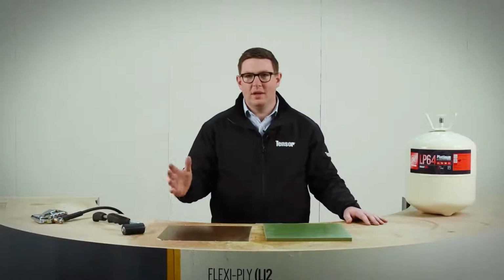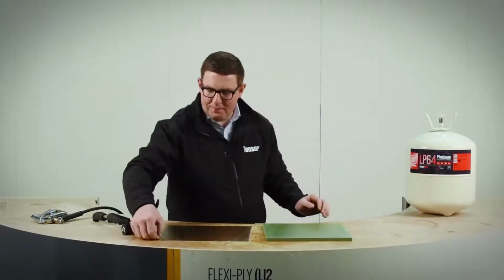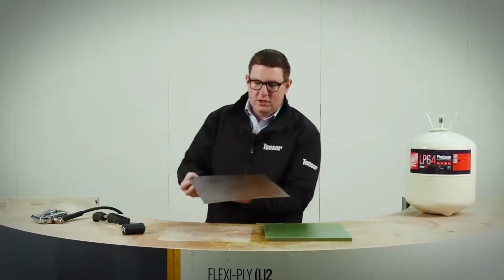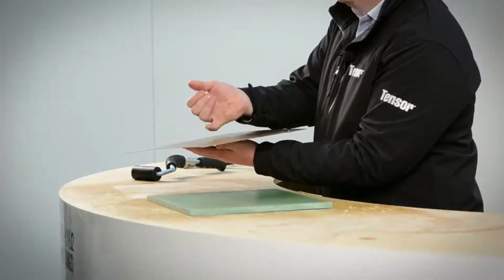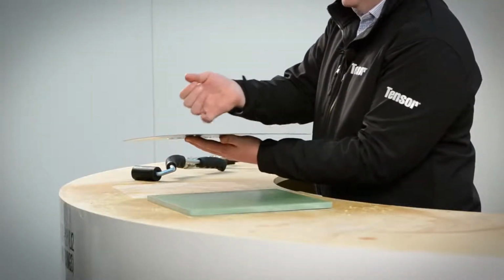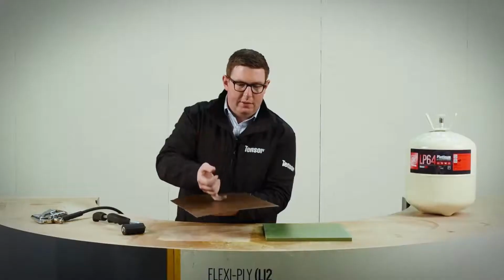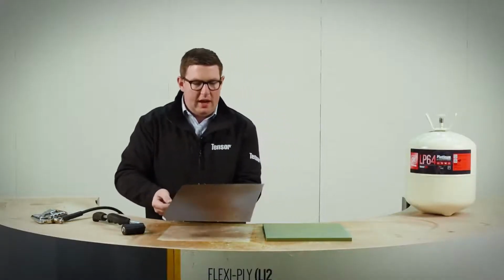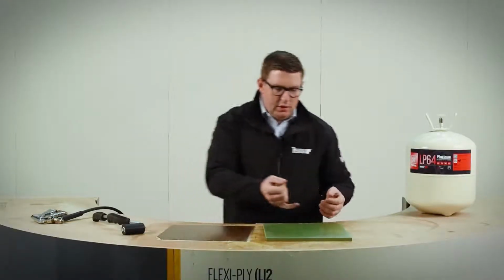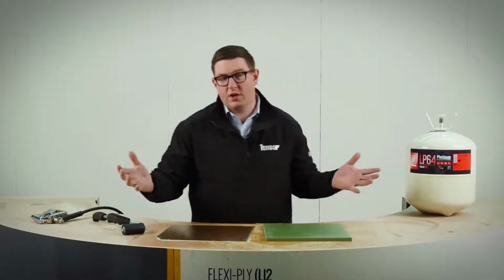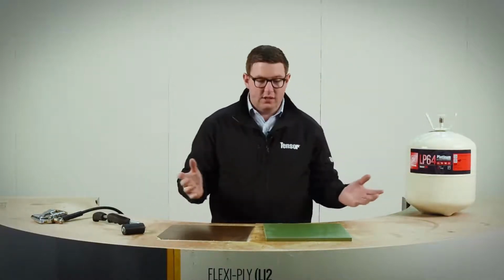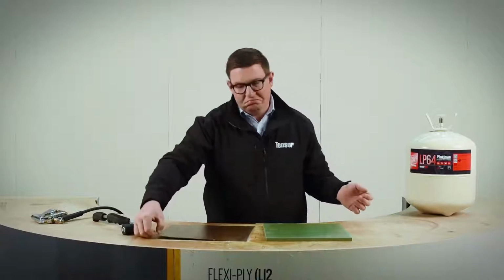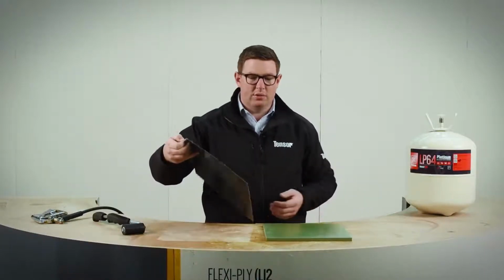We're back again, 3 minutes later. Okay, so here we go. This is the surface of the laminate. There's literally very little tack to this. I couldn't actually lift the panel off. It's dry and it's very, very flat. So 3 minutes, this environment's 20 degrees. It's dry, it's a very, very clean environment. So in this environment, 3 minutes was ample.